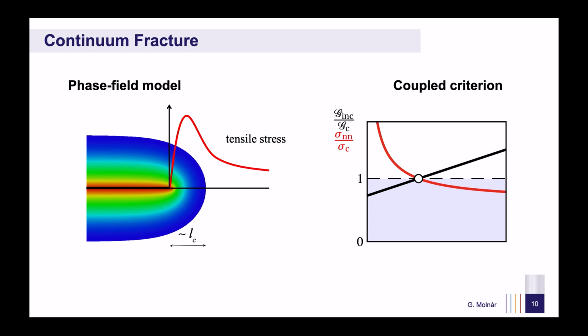In the first scientific part of this presentation, I will show how the length scale parameter in the phase field model enriches linear elastic fracture mechanics. I will focus on simple cases where the size effect is most evident. However, we treated phase field simulations as numerical experiments, essentially as black boxes. To better understand the results, we turned to finite fracture mechanics, more precisely the coupled criterion, to explain the observed behavior. This powerful technique helps interpret automatic results produced by the phase field approach.